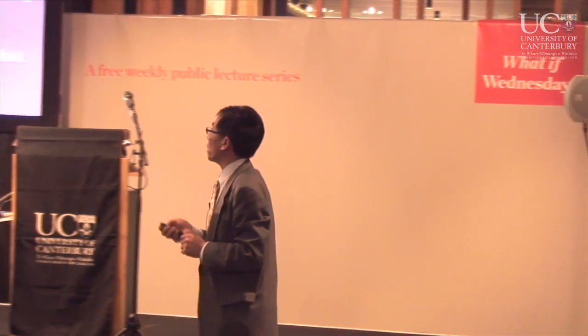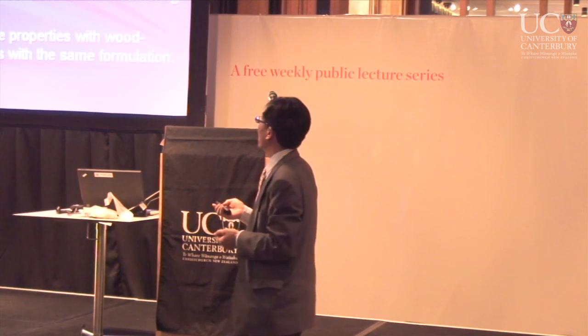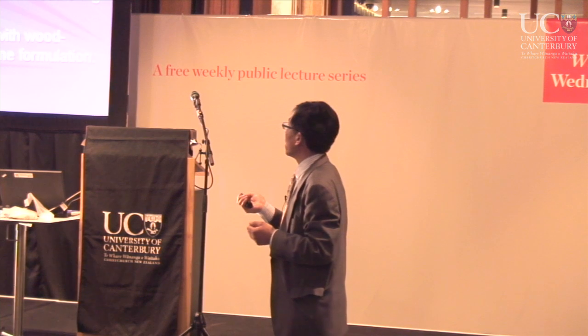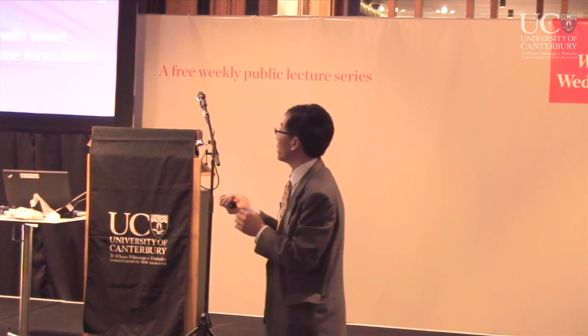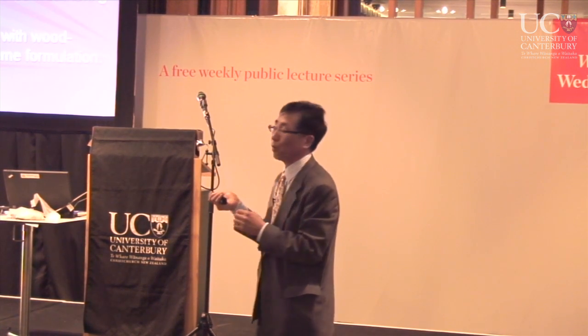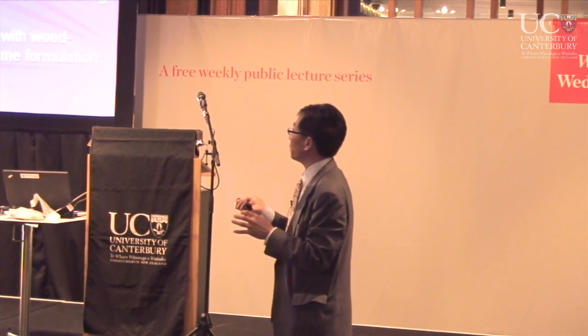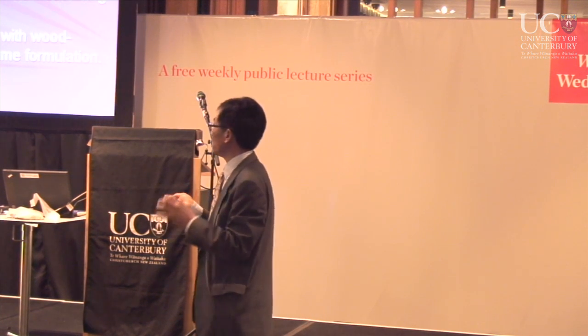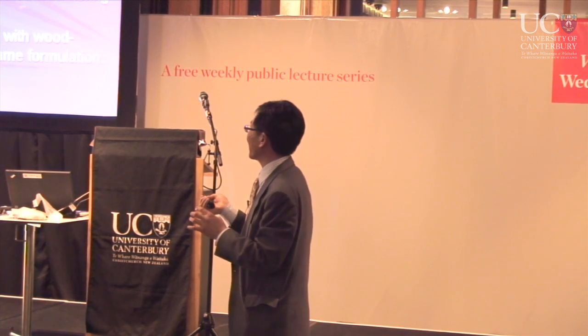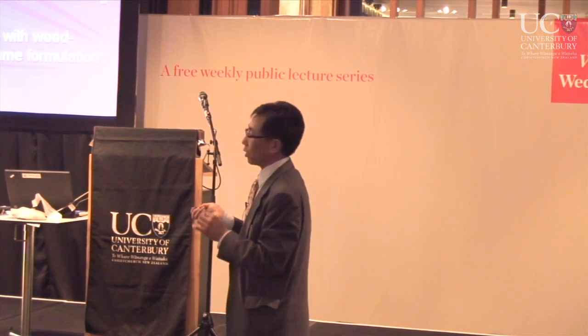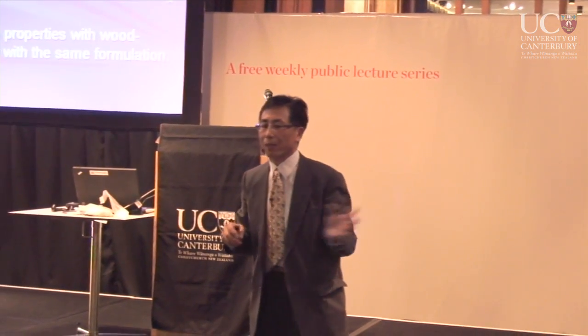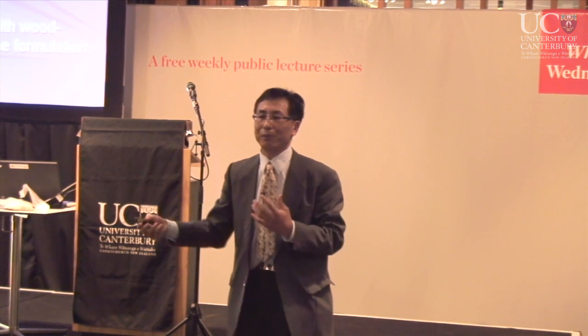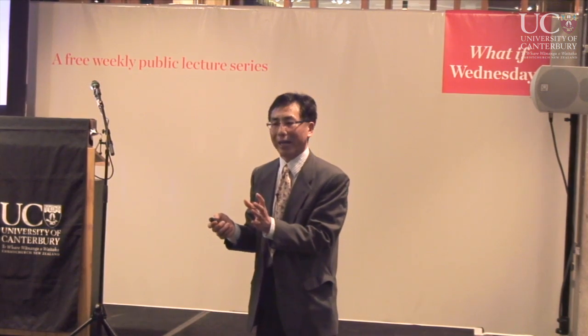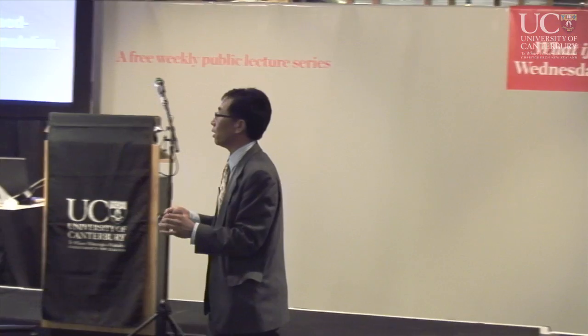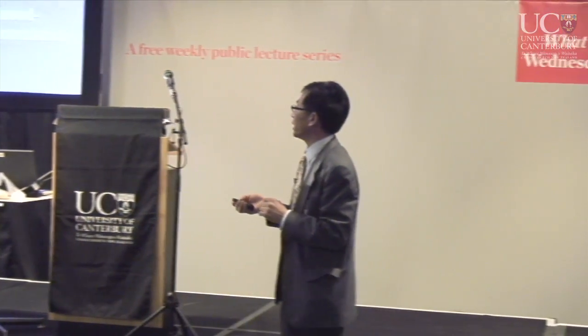Okay, so what's new in our work? As I mentioned, we use recycled plastic. We use the hot press molding process. We use optimized processing conditions to make the product which has the most desirable properties. We test the materials for stability, durability, strength, stiffness, and accelerated weathering conditions. Of course, we cannot leave the materials in a natural condition, because otherwise it would take many years. Even after my retirement, testing of the material durability would still be going on. So we have to use a way to accelerate the weathering condition to test the materials. I will tell you how we did that later on.